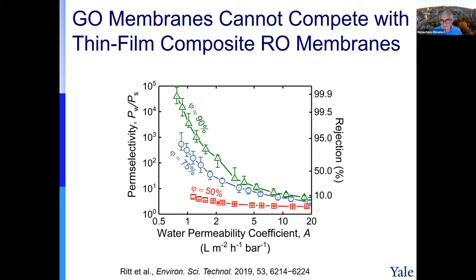Let's take an experiment with 50% coverage, and you create such a membrane. So you start somewhere here. And as you create the membrane, it becomes thicker and it is more difficult for the water to go through the membrane. So the permeability decreases because the water needs to go through a more tortuous path. And we stopped when the permeability reached 1 because anything less than 1 is not efficient. You will need more energy. And with such a membrane, we were not able to get more than 10% rejection, which many laboratory experiments show. Then we said, let's have 75% coverage, which is the best experiment they were able to get.